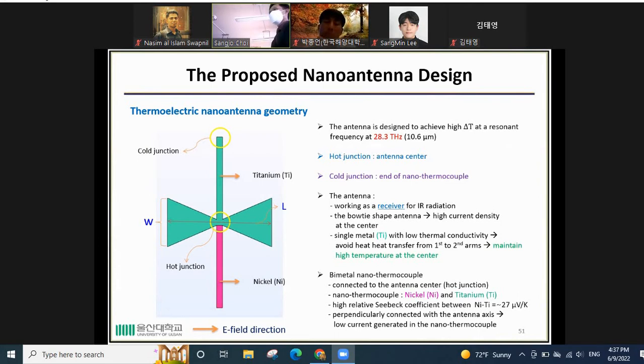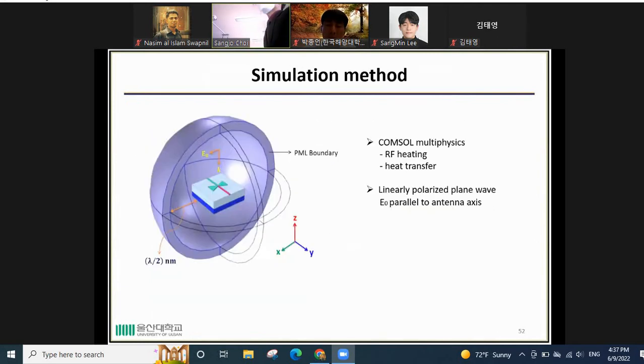And also we connect a bimetal nano thermocouple, which is made from nickel and titanium, to the antenna center. We choose nickel and titanium because of the high relative Seebeck coefficient, around 27 microvolts per Kelvin. We also connect this nano thermocouple perpendicular to the antenna axis to avoid current generated in the nano thermocouple. And this is the simulation method. We use COMSOL multiphysics, using RF modeling to calculate the current density and also heat transfer to calculate the temperature difference. We also use a linearly polarized plane wave, where the electric field is parallel to the antenna axis.